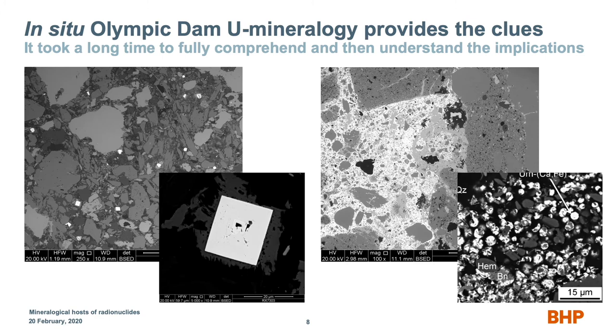So we're going to jump ahead about a billion years, and in a sample that has a very similar kind of scale across it, we see a lot of bright whites, and those are actually high-grade uranium, and it's in the hematite sulfide matrix. But when we look down at the little particles that make it up, they're not an individual crystal, they're often these little tiny balls of stuff. And you see the 15 micron scale bar, they're little. And these things just move around over and over and over again.